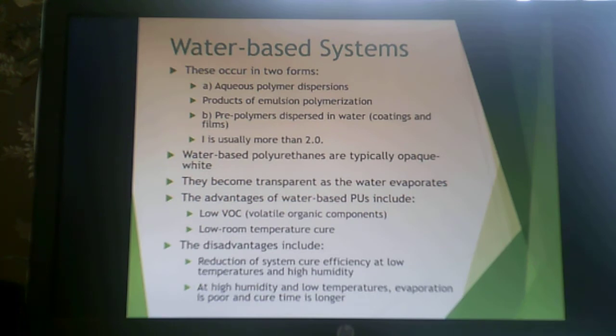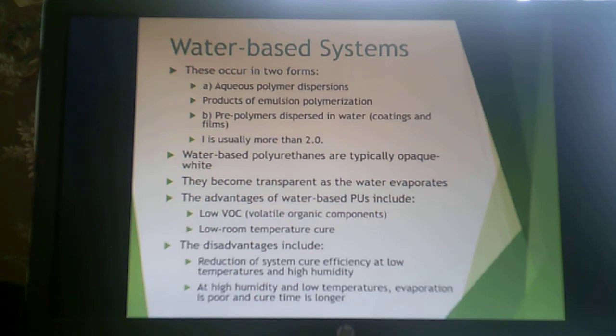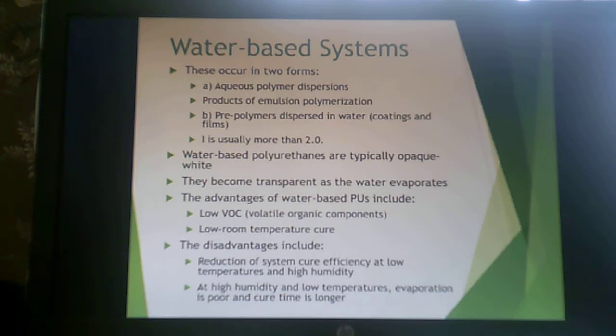There are also water-based polyurethane systems — aqueous polymer dispersions that are the product of emulsion polymerization. You have a pre-polymer dispersed in water for coatings and films, and the isocyanate index is often more than two, giving lots of extra isocyanate. Typically the polyurethane is opaque white, and after the water evaporates it becomes transparent. If you're coating a piece of furniture and it is cloudy, this is typically what you're dealing with. Not to be confused with polyacrylic, which can also come out cloudy but is only a little cloudy — these are typically very white.